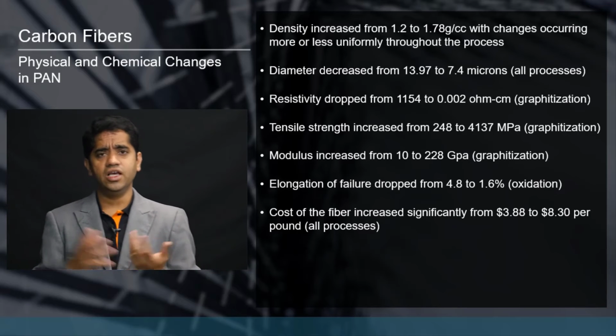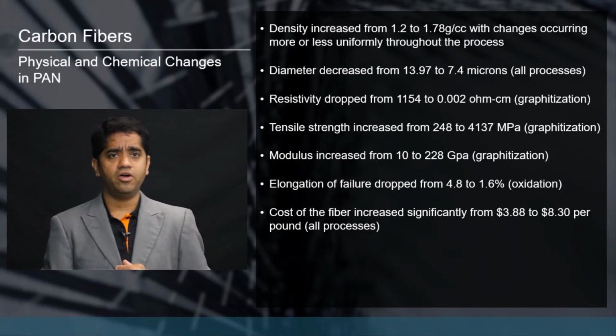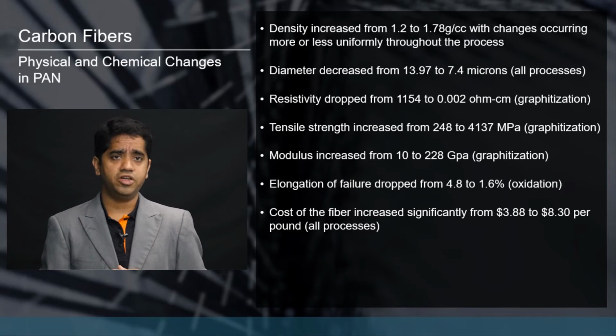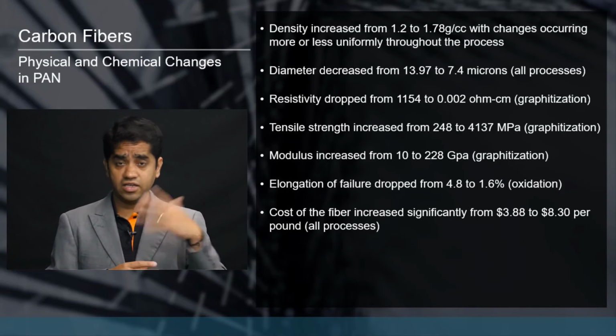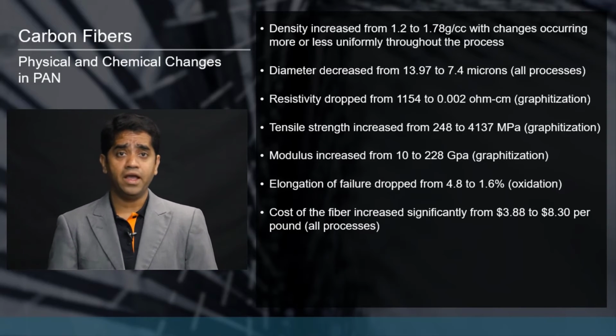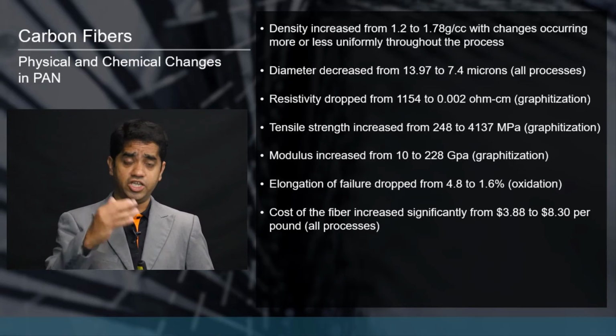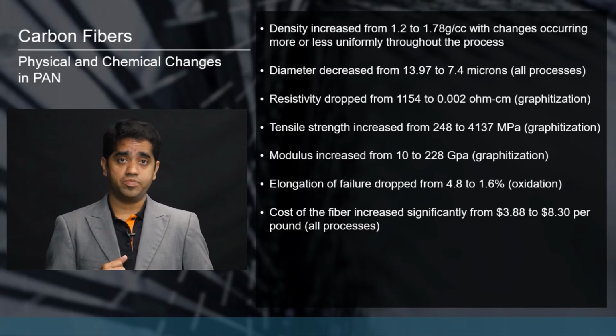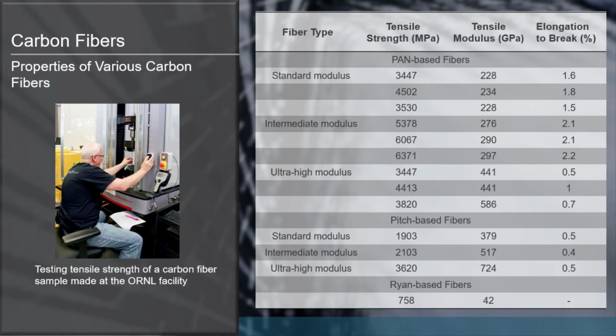Because for the standard modulus, you may get it at around $10 to $20 per pound, and then intermediate modulus may be around $20 to $30, and then ultra high modulus is significantly higher than that. And each of them will have a specific application requirement when it comes to automotive or aerospace. And you can see these are the properties that we are talking about. As you can see, the tensile modulus between standard, intermediate, and ultra high is significantly changing, anywhere between 230 to 270 to 400. And that is for the PAN based, and for the pitch based, it's anywhere between 300 to 700. And Rayon is nothing but the cellulose based, which is again one of the lowest.